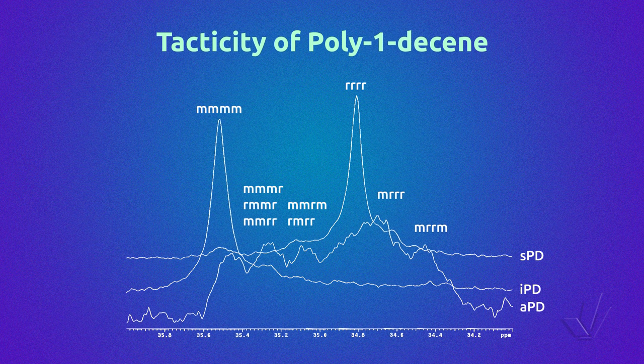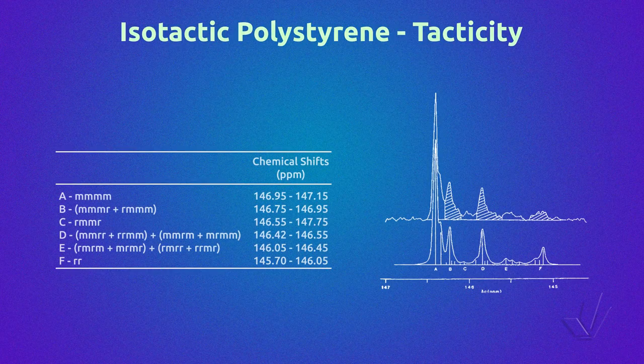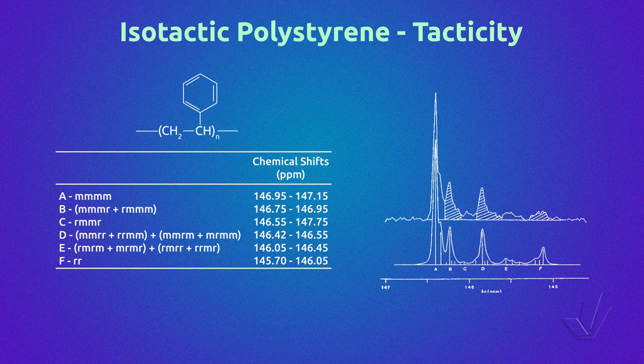Here we have the expansion of the spectra in the ipso carbon region with the assignment. As can be seen, pentad resolution is not as clear as it was with polypropylene. However, some pentads such as the isotactic mmmm or syndiotactic rrrr can be distinguished from the others to have an idea of tacticity. The calculation of tacticity of polystyrene by carbon-13 NMR was also studied. The carbon atom used for this determination is also the alpha carbon from the methine carbon, and in this case it is an aromatic carbon.